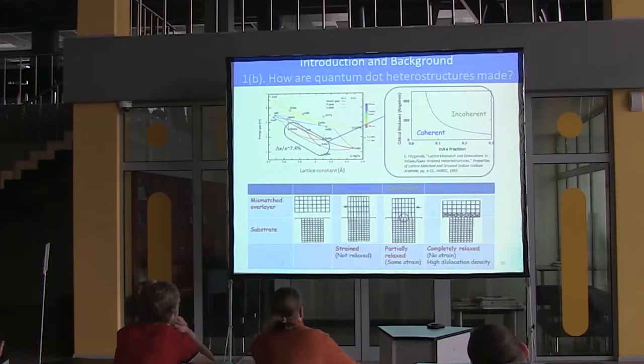And what you see, and this is kind of like a Matthews-Blakeslee theory as they call it, you see that depending on the system, and this is indium arsenide, as I move along here adding more indium, all the way to finally go over here, you find that with more indium, there's more strain, so the critical thickness before this thing dislocates and forms and doesn't really basically work for me at all, and I'll tell you what I mean by that in a second, is rapidly diminishing. By the time I get to indium arsenide on gallium arsenide, I can grow on average 1.6 monolayers. If you look by STM, scanning tunneling microscopy, you'd see about 1.6 monolayers. Not really working for you.